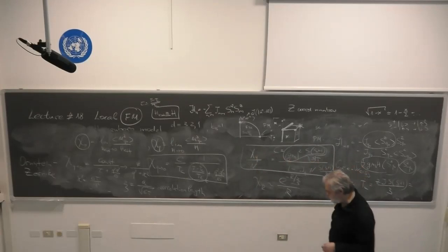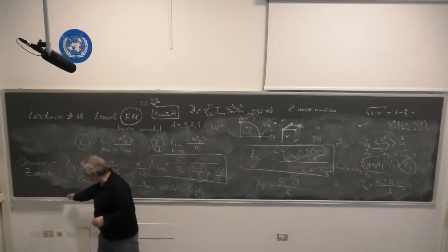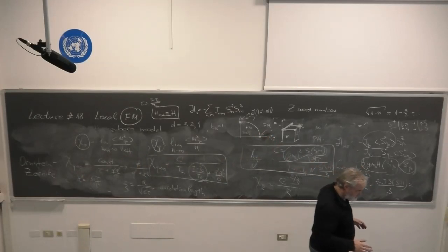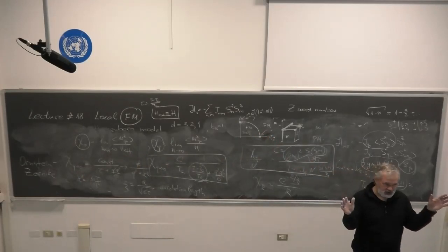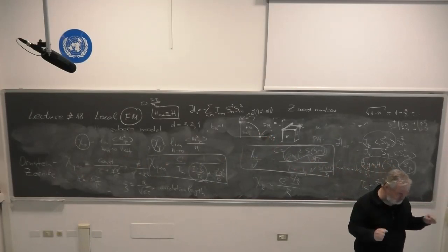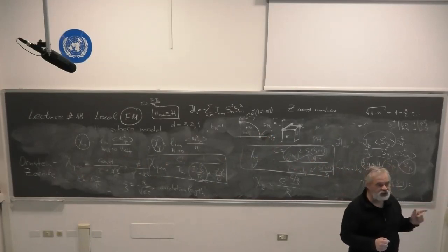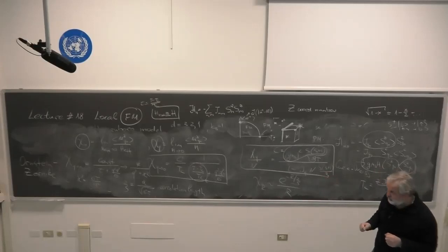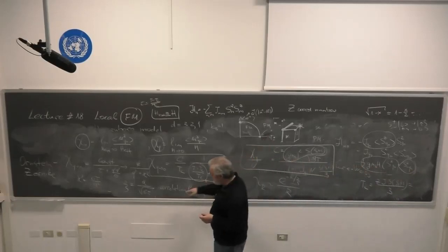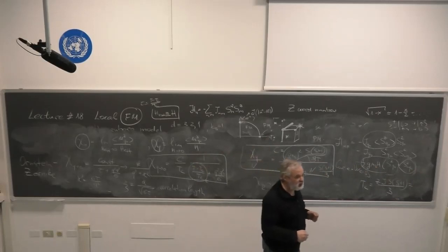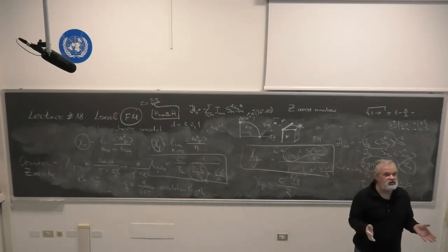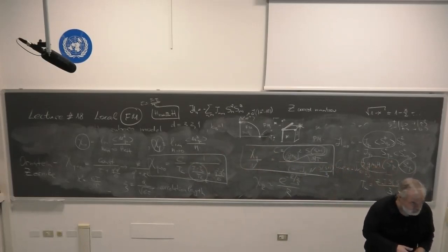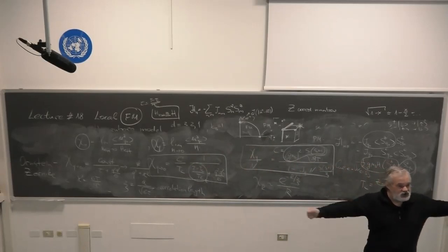This is the last comment which I would like to make. Physically, what happens? You are at temperatures above the critical one. You are in a paramagnetic phase. However, you lower your temperature in such a way that you approach the critical point. You are considering a model with a short range interaction, namely only nearest neighbors interact. However, you see that by approaching the critical temperature, your spins start to be correlated with a correlation length which is inversely proportional to the small parameter which describes the closeness to the phase transition point. The more you approach, the larger the correlation length